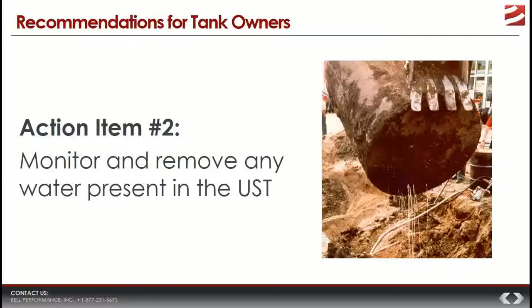How do you know, if you didn't know you had a corrosion problem, that your ATG apparatus hasn't been damaged by corrosion? You don't, unless you verify the results manually at the same time. Now, how much water should be of concern? It really doesn't take much water at all for a microbial problem to manifest itself. Less than a quarter inch is more than enough.